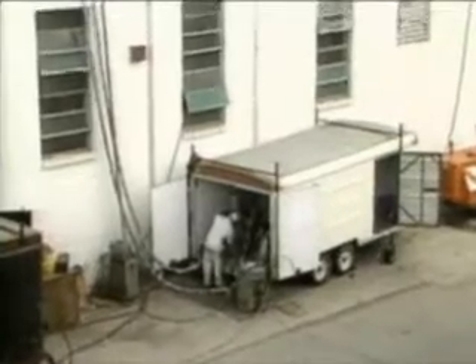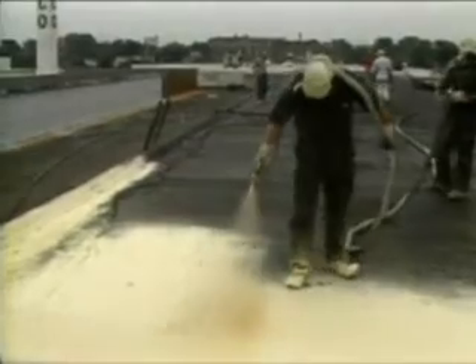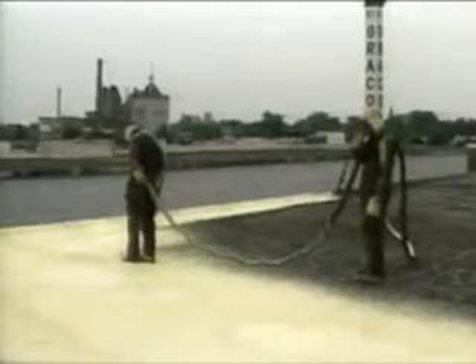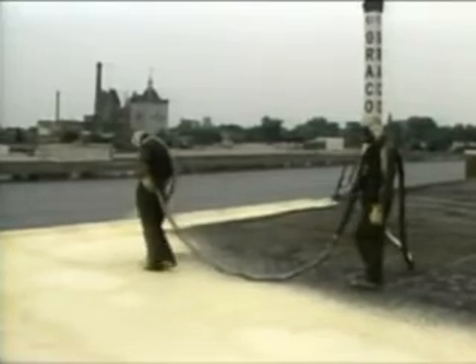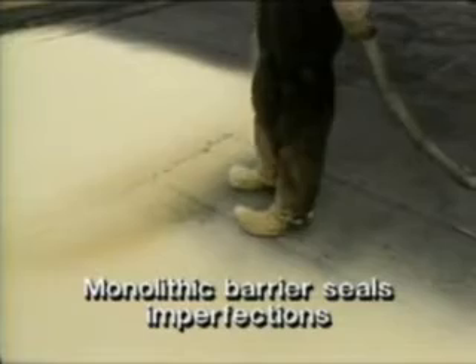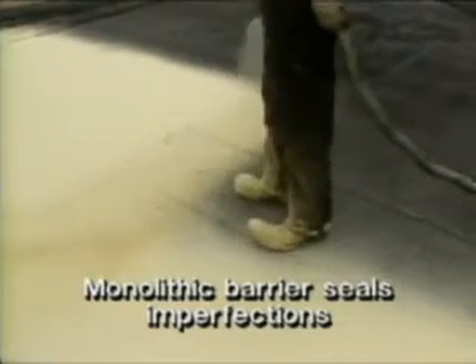The roofers applied the foam using a plural component proportioning pump that furnished heated material in exactly equal proportions to a spray gun which mixed the material at the head and atomized it into a spray. This equipment can foam several thousand square feet per day with a relatively small work crew. Immediately, the urethane began to rise to 30 times its original thickness, forming a 1.5 inch deep layer in just 30 seconds. The foam developed into a monolithic closed-cell barrier sealing all the old imperfections.